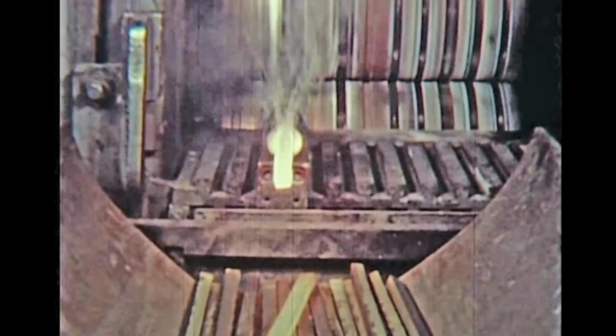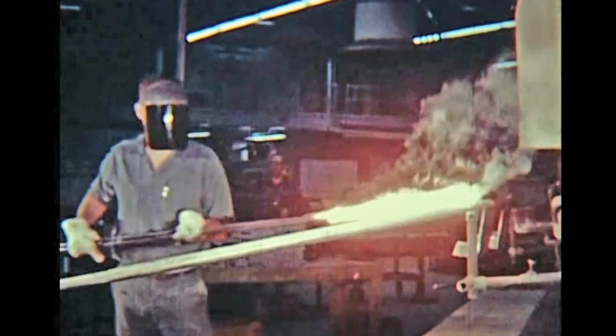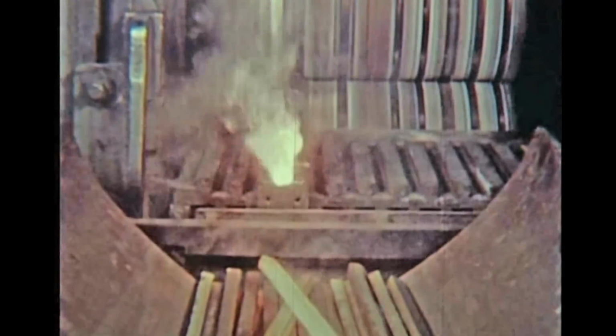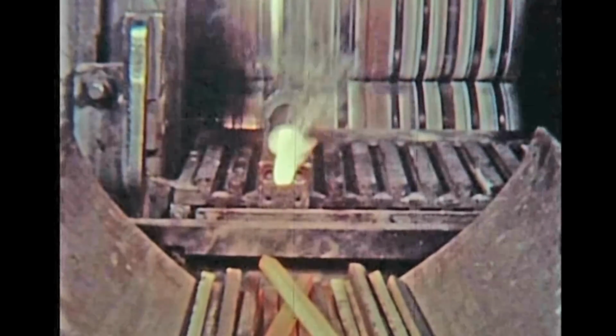As the ingots are rolled, they increase in length and reduce in cross-section. Several different passes will be made through the mill until the ingot, now essentially a square rod, will become round in cross-section. When the rod is about 3/8 of an inch in diameter, it is swaged on the number 4 roll feed machine. The end is preheated before it is pushed through the swaging die. The rod is heated in the furnace to about 1400 degrees centigrade, and then enters the die and is swaged to size. Power-driven rolls continue to pull it through the die and onto a trough.